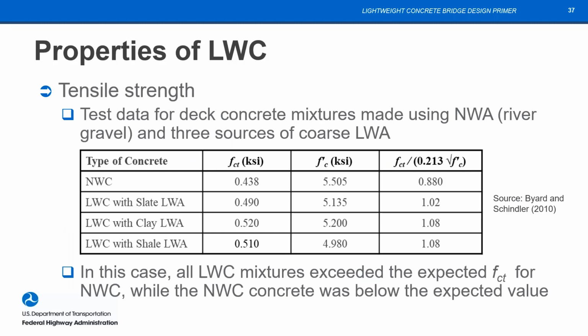Tensile strength: oftentimes people think that the tensile strength of lightweight is going to be reduced compared to normal weight. There was a study done at Auburn University. This is data from that study. In this case, the splitting tensile strength is shown here, the compressive strength here, and the ratio of splitting to the expected splitting tensile strength for normal weight concrete is shown in this column. We actually find that all the lightweight concretes have a ratio greater than 1, whereas the normal weight, which was a river gravel, had the reduced tensile strength.